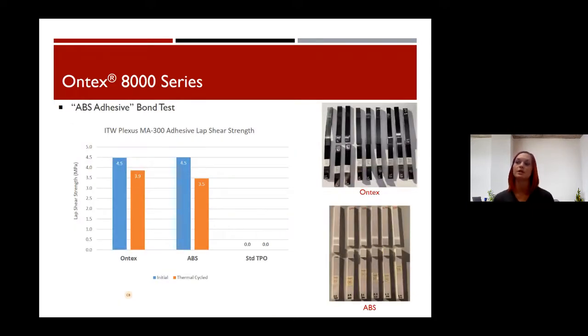And then we also did a lap shear test for bond strength, where we made these little plaques. We bonded ABS as a control, as well as the TPO with Ontex. And we kind of took a poll of some of our main thermoforming customers and asked, what do you use to glue ABS to things? And a popular one is that MA300 from Plexus. So that's what we used. And you can see the Ontex performed just as well as the ABS. So we were very happy with that. Also, the standard TPO, you can see it didn't stick at all, which is what we would expect, but just to make sure. So we tested those and everything looked pretty good from that point.